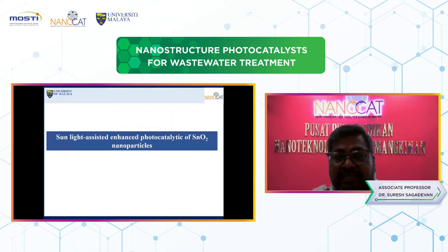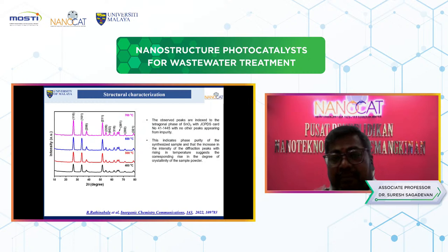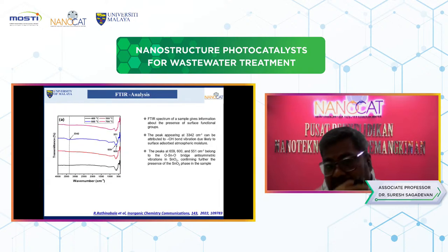And then the next material: sunlight-assisted enhanced photocatalytic activity of tin oxide nanoparticles. This tin oxide nanoparticle was prepared by a chemical method, using four different calcination temperatures: 400, 500, 600, and 700 degrees Celsius. From the XRD pattern, we observe the tetragonal phase of tin oxide, which is indicated by the planes. This indicates the phase of the synthesized sample. You can look at here, increasing the temperature increases the intensity of the diffraction peaks, corresponding to an increasing degree of crystallinity of the prepared sample, as well as the FTIR spectrum of the prepared tin oxide.